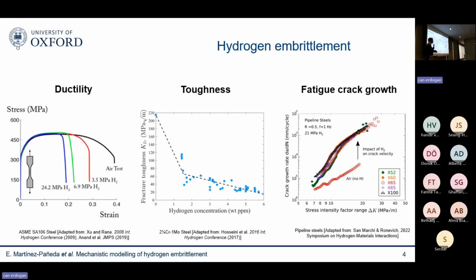So this is ductility, uniaxial stress-strain curves. You can see that if you expose your metals to hydrogen, for example, exposing them to hydrogen gas, then you get a very significant reduction in ductility. Even more significant is the effect on fracture toughness, as you see here in the center. This is for a pressure vessel steel. You can see that 6 parts per million of hydrogen, a tiny amount of hydrogen, is sufficient to bring down the toughness of a pressure vessel steel from above 200 megapascal root meter to below 20 megapascal root meter. So an order of magnitude drop, going from a very ductile metal to almost an engineering ceramic.